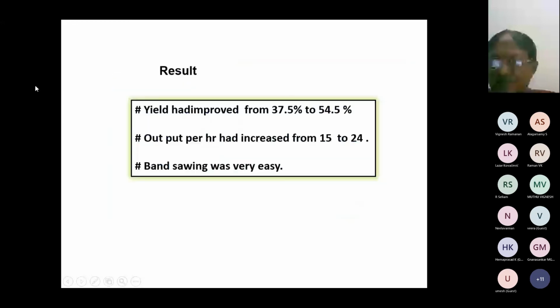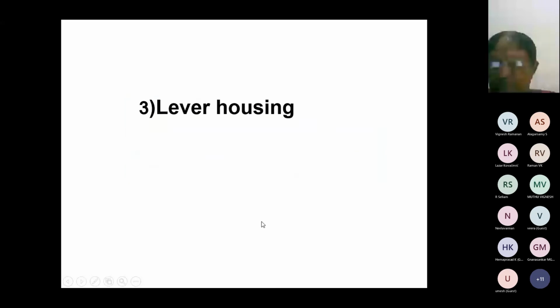Yield has improved from 37.5% to 54.5%, and output has gone up from 15 to 24 numbers per hour. 24 into 2 castings, that is 48 castings per hour, we are able to get. Band sawing was very, very easy. This was the one success story.